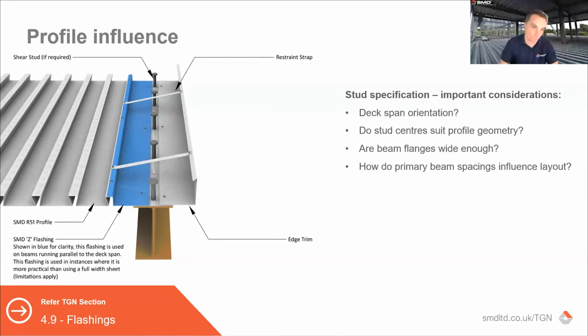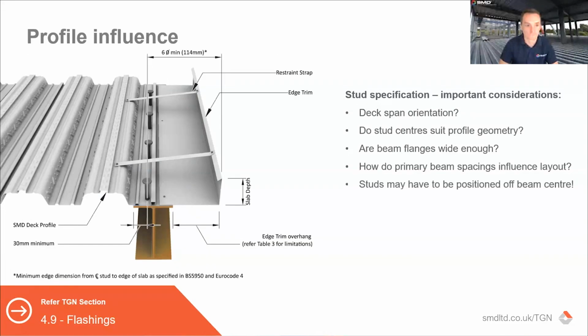And you also, or we may have a, rather than actually cutting the profile back like that, we may be putting just a Z profile on the very edge of a sheet just to close off that edge, similarly giving you the ability to weld to that edge beam or internal beam if it's in an intermediate primary. Just a point to note, and this is more likely at edges, but also you can have it at internals, that studs may need, due to the profile setting out and due to slab edges, to be off center. So there are instances where the studs have to be welded off center of beam, and that is very common, I would say, because it'd be very difficult to achieve at the center of a trough on every beam. So it's common to see studs off center, particularly at edges where there's a minimum dimension to the edge of the slab if the edge beam is designed as composite.